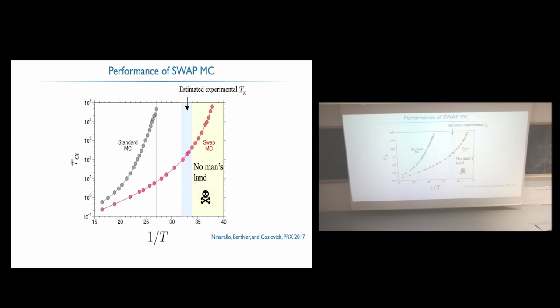So again, the same plot, the relaxation time as a function of 1 over temperature. Now the top regime is the 10 to the 5, because this is where we cannot run simulations longer. So with standard Monte Carlo, you get this increase. And now for the same temperature, you put swap on, and boom, you get a massive reduction of the time scale. And it means that you can get this branch here in red. So you can equilibrate on all these temperatures.